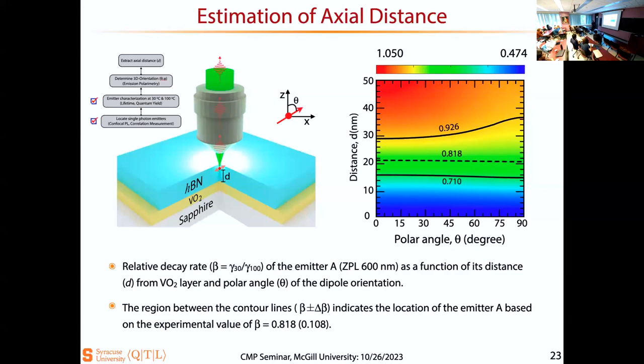So using COMSOL simulation, we extracted how the ratio of the lifetime at room temperature and 100 degrees Celsius looks as a function of the distance d and also the polar angle, because the polar angle is also an important part when you have an interface. The dashed line is the experimental value of the ratio of the lifetime. And the solid lines are there because every experiment has an uncertainty when we extract the lifetime, so these two solid lines show the uncertainty.